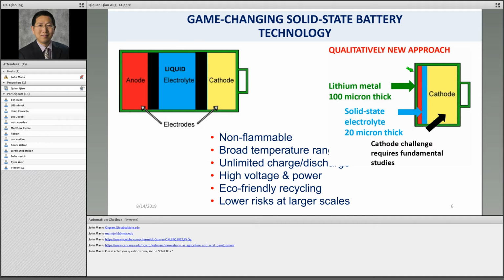And then with that, if you look at these structures, you can see here. I'm not sure, the mouse does not work. The lithium metal can be here, and then you have solid electrolyte, and you have the cathode materials here. You can make the batteries very compact, very small, compared to liquid electrolyte. You worry about the leakage and also the materials you use as an anode. So with solid state, you can get a lot of benefits, like non-flammable, broad range of temperature operation, unlimited charge-discharge, and also high voltage power, eco-friendly recycling, and low risk at larger scales.